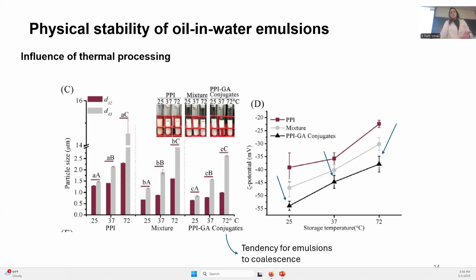We do see that the pea protein alone had a bigger particle size compared to the mixture and the conjugates. However, we also don't see much difference in particle size between the mixture and the conjugates. We do see a difference in charge. We can see, which is the black line, the conjugates are more negatively charged compared to the PPI and the mixture. That can lead to more stability during thermal processing.